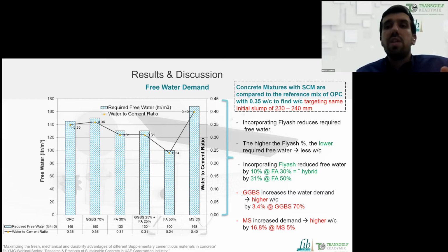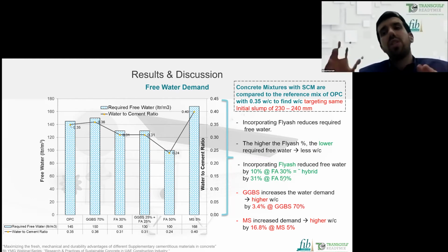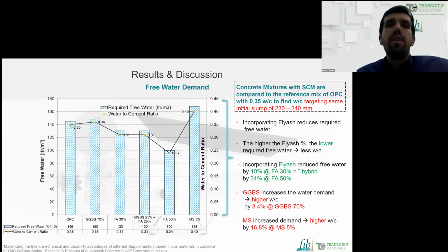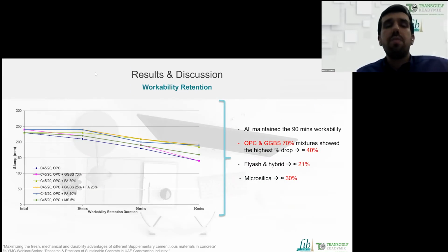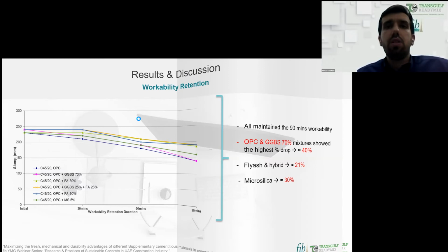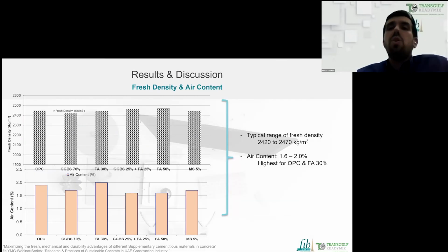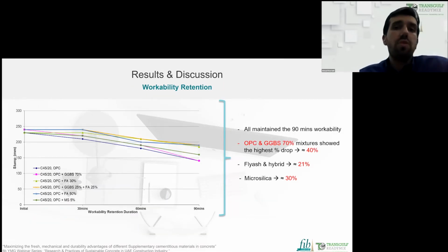Incorporating fly ash, I can say it reduced the free water by around 31% when we have a 50% replacement, while it dropped the demand by 10% when we had a 30% fly ash incorporation, which was similar to the hybrid. For slump retention, all concrete mixes give a good slump retention, evaluated in this study up to 90 minutes.